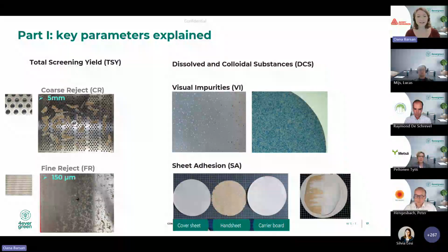Now, the recycled paper is made between two other sheets, a cover sheet and a carrier board, and the way that this is removed from the two cover sheets is how the sheet adhesion is determined. There is a knock-off criteria with this parameter, essentially meaning that if the sheet cannot be separated from the carrier board and the cover sheet, then that means that particular product has failed the recyclability evaluation and no testing is needed further.